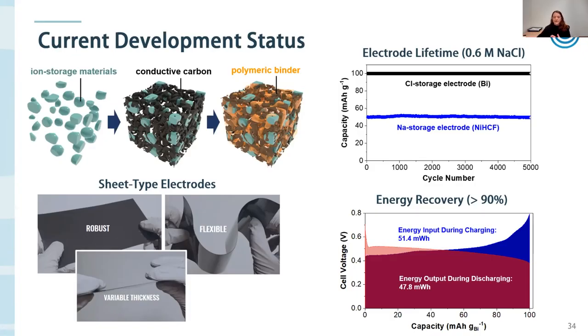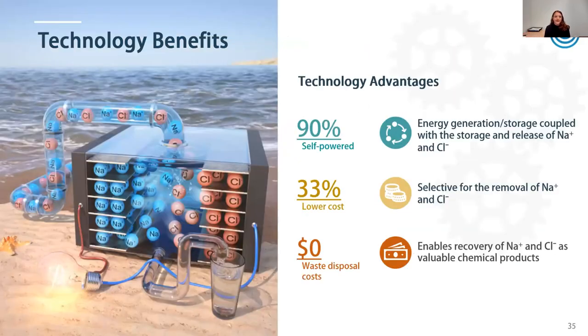The other thing that we looked at when we did these experiments is the energy recovery efficiency. So I mentioned that our system produces energy during the desalination step, which you can see by this red curve here, and consumes energy during the electrode regeneration or resource recovery step, which you can see is this blue curve here. And so in our optimized system, we can achieve an energy recovery efficiency of over 90%, which is really encouraging. Another way to think about it is that our system is about 90% self-powered. And that's one of the really big benefits of this type of electrochemical desalination method.